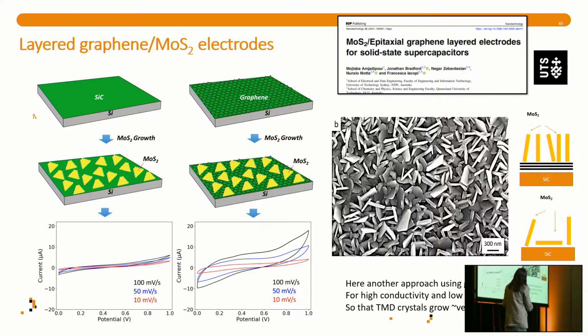I'll go just very quickly here. We noticed something really interesting by coupling MoS2 onto graphene, so growing MoS2 onto graphene on silicon carbide on silicon, that we could have this quite interesting effect of growing the crystals of MoS2 almost all vertical, compared to if we had done that, for example, with silicon carbide, which was also quite interesting in terms of behavior. So the idea, of course, is that we can make planar electrodes and integrate this as a tile of those 3D system approach.